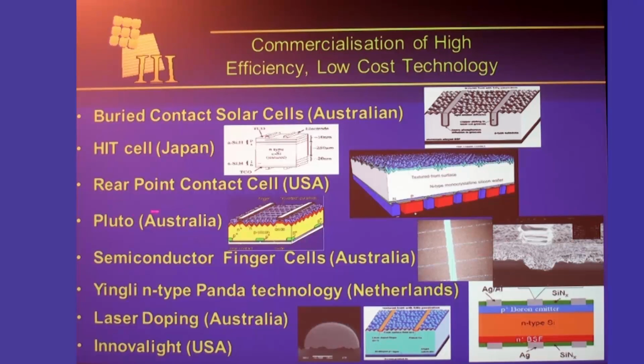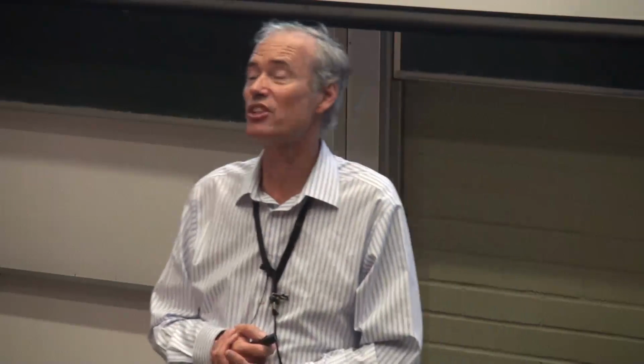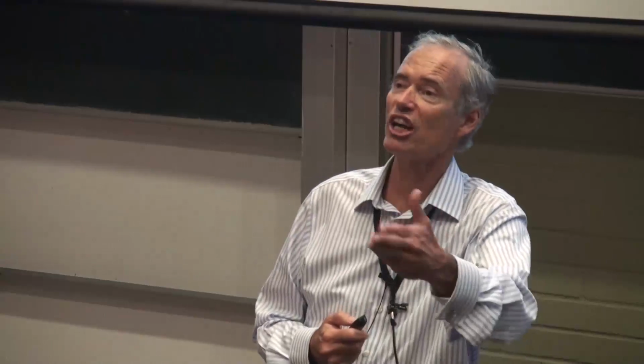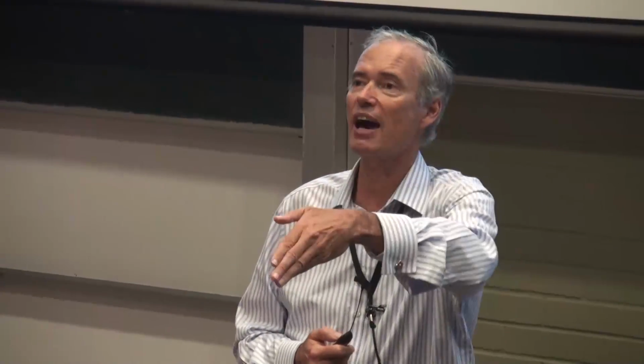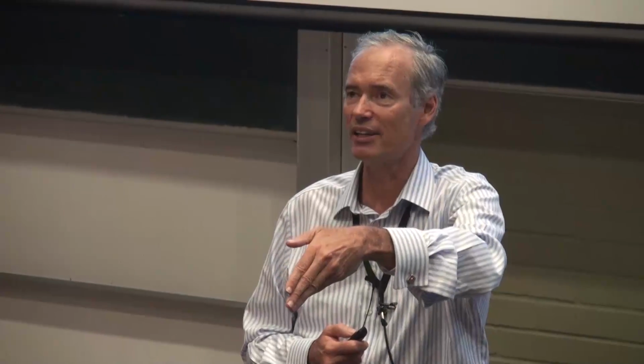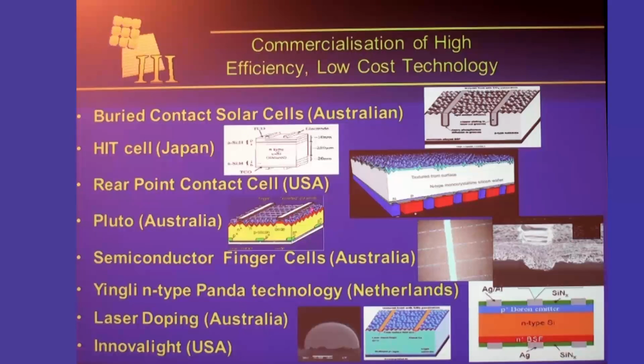But what Suntech has been able to do is reduce the price of this solar cell by 99%. Right? 99% reduction. And of course you can't do that with titanium, palladium, silver, because it's not just how expensive those metals are, it's the way we used to have to deposit them as well. Very, very complicated to form such narrow strips here where the metal would go and then to form the metallisation. Very, very expensive to do so. Suntech has come up with a very simple, low-cost way of patterning the dielectric. They've developed a great plating technology where they basically use copper for their metallisation.